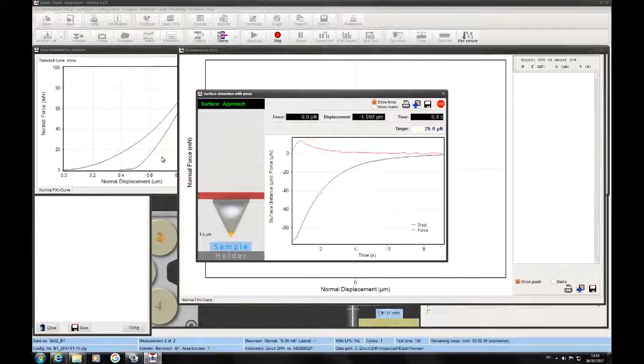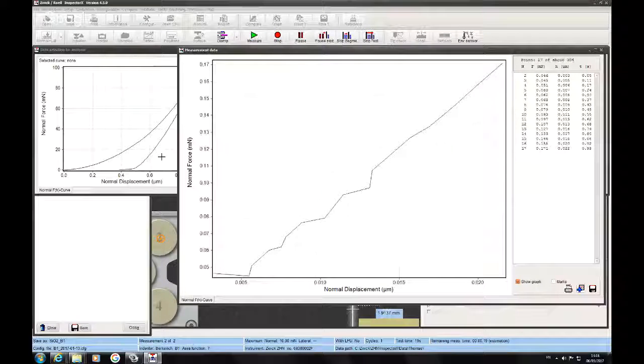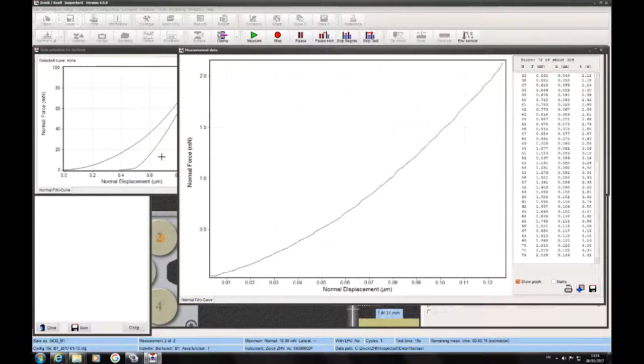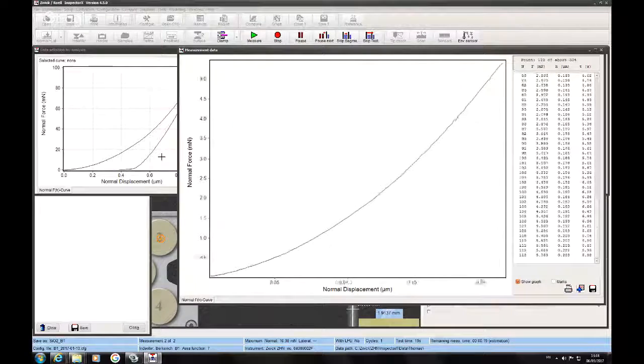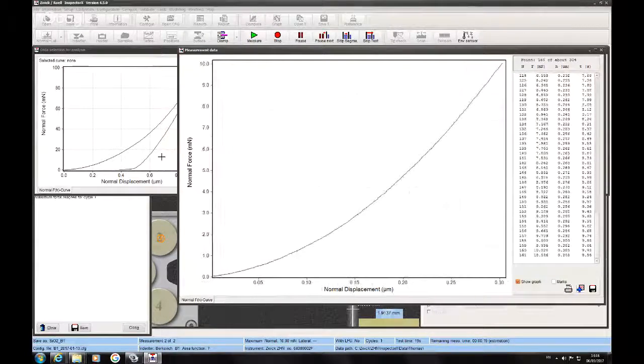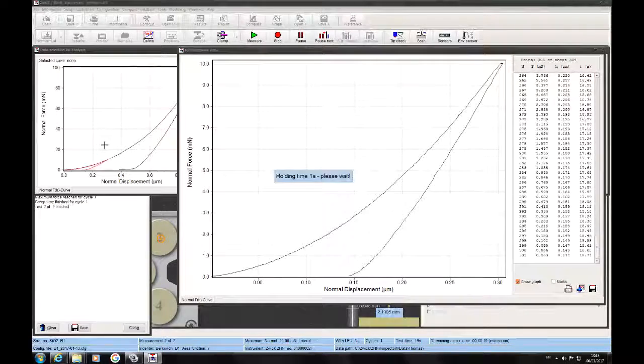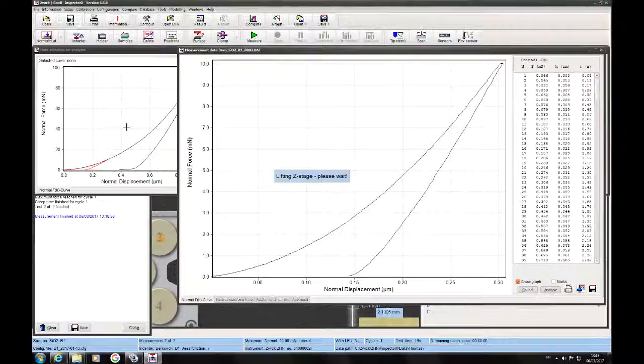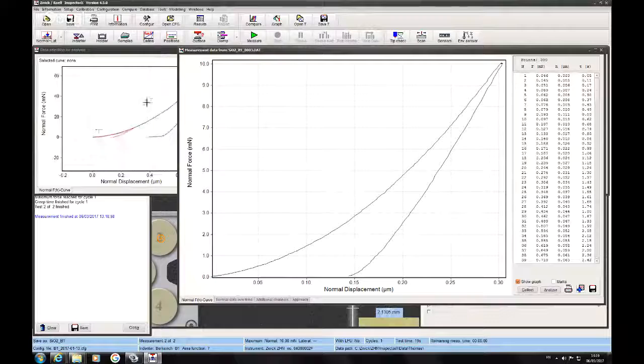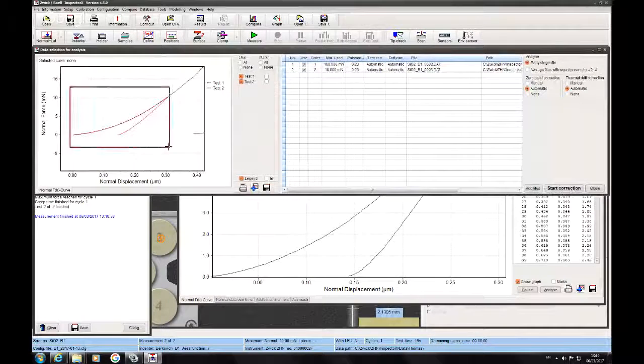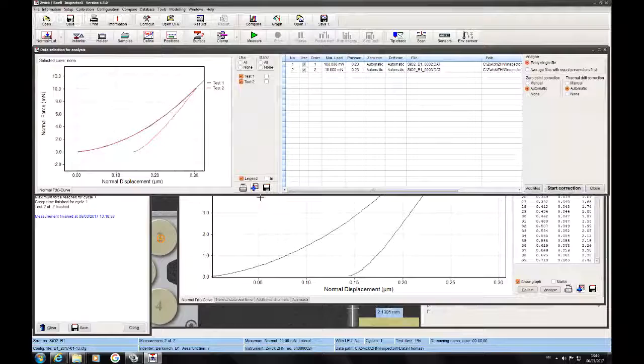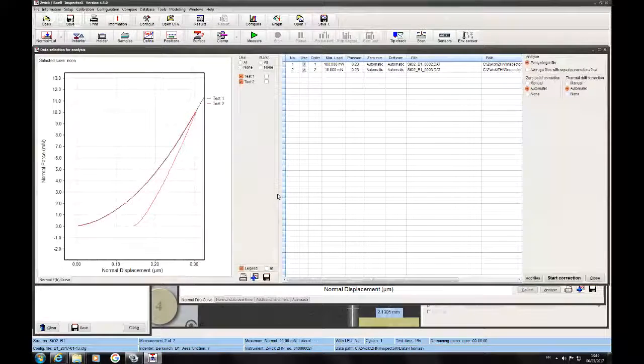This shall be now with 10 millinewton only. Creep time again, and unloading will follow. You see in the other window that the loading curves agree quite well. After the end of the measurement, the tip goes up again, 3 millimeter for security reasons. Of course, you can magnify that to see it better.